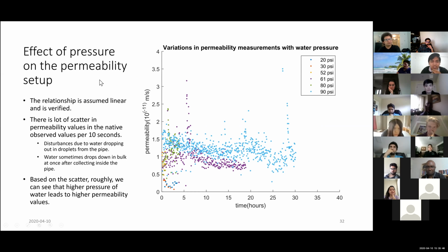So then I wanted to see the effect of pressure on this permeability setup, and the relationship is assumed linear as per the equations of permeability in a hollow cylinder. But while I observed the test, there is a lot of scatter in between the values. So we can see that roughly the blue, which is at 90 psi of water pressure, has higher permeation than 60, and then these two values which are lower. But it's really difficult to observe this just using a permeability measurement. So there is a lot of scatter and a lot of disturbance.